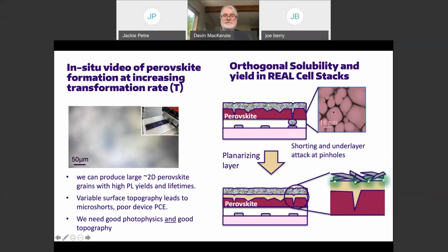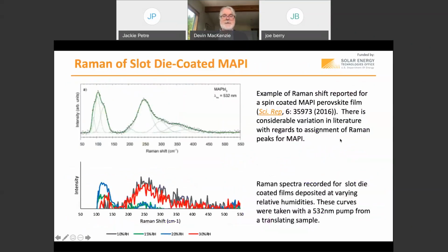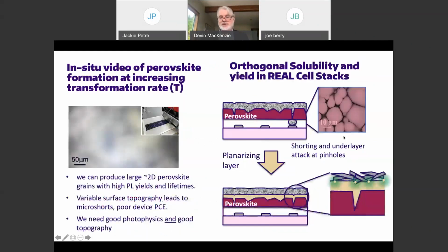We're not there yet. But we think that's a really interesting area for us, because as you move to continuous processing and slot die coating, it's a much more controlled, linear process, with a much more controlled transformation rate. We have the ability to grow textured grains, and much, much larger grains. On this grain boundary problem, people have done some novel stuff, putting interesting things in to fill those grain boundaries and enable this large grain structure. That's a real opportunity. So that brings up the question that we need to monitor structure.